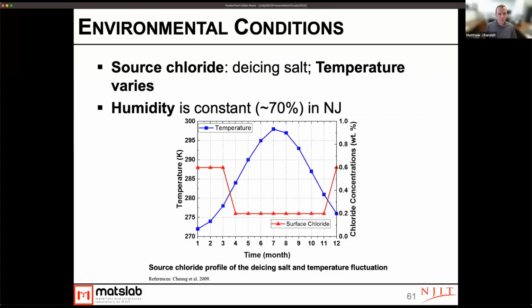And so we had a chloride source, which was from de-icing salts, and we looked at temperature variations. New Jersey has a relatively constant humidity as compared to other environments, especially compared to what we could sort of simulate in the laboratory. And so what we applied to our computational model were these simulations of basically chloride exposure in certain months, and then temperature swings over the course of a year. And we repeated this for basically decades in our computer model to simulate how long it might take to see chlorides at different thresholds, or what the corrosion might look like at different points in time.